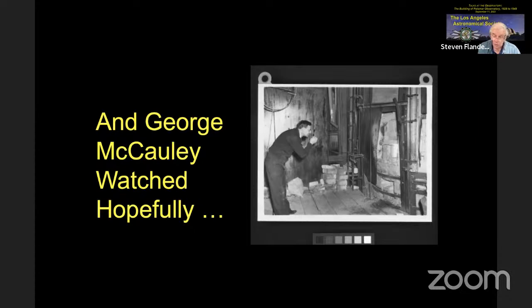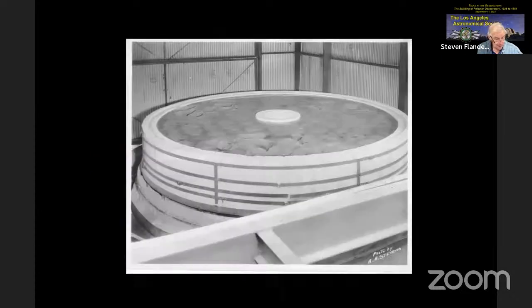But then soon after lunch, first one, then two, and then several of the ceramic cores became detached and floated to the surface of the glass. Well, as would become apparent later, the hot glass had melted the steel bolts holding the ceramic plugs to the bottom of the mold. The 20-ton disc was ruined as the free-floating plugs left deep scars in the disc's upper surface. In the early spring of 1934, failure represented a substantial setback to the project. Needless to say, Corning Corporation was deeply and very publicly embarrassed, so much so that the failed disc shortly found an appreciative audience among the many paying visitors to the Corning Museum of Glass, where it still resides.